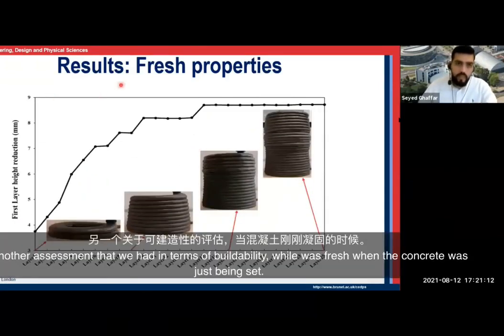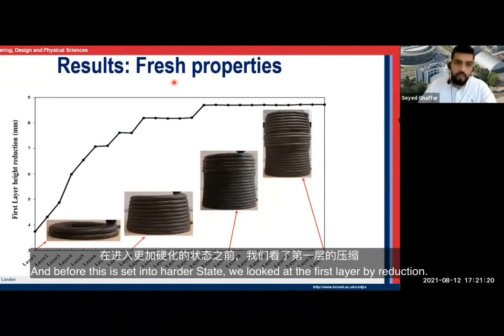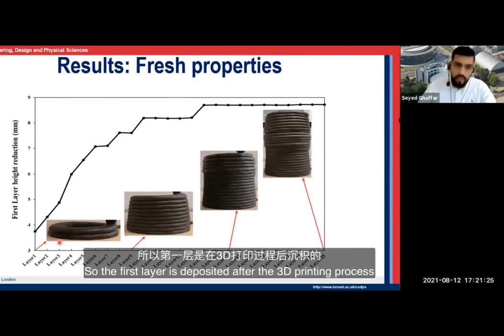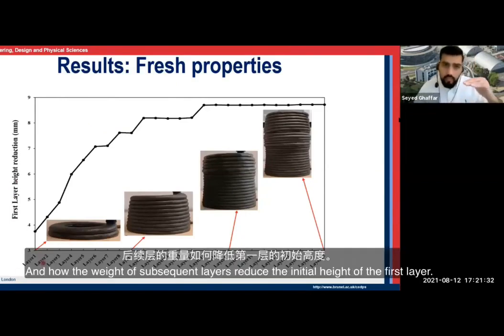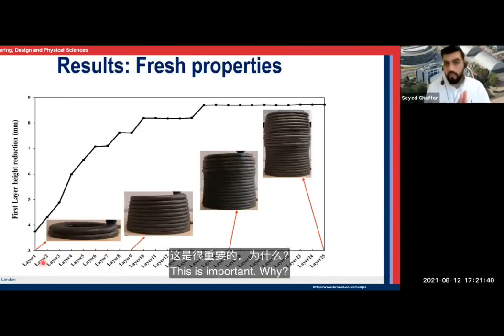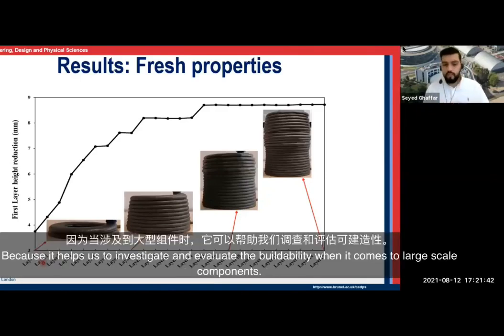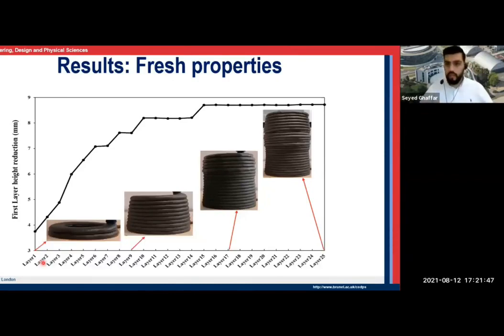Another assessment that we had in terms of buildability, when the concrete was fresh and just being set, before it's set into a hardened state, we looked at the first layer height reduction. So the first layer that is deposited in a 3D printing process, and how the weight of subsequent layers reduces the initial height of the first layer. This is important because it helps us to evaluate the buildability when it comes to large-scale components.